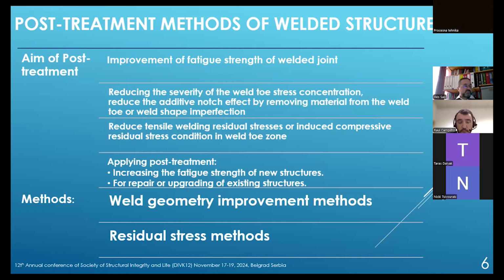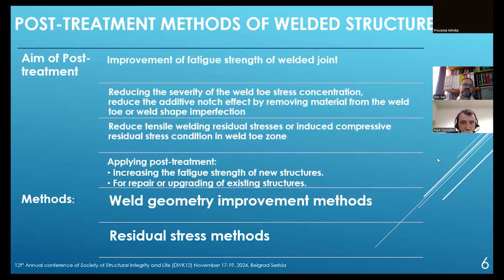What is important in the case of post-treatment is that some of the post-treatments can be applied not only after the manufacturing step, but also later when we detect imperfections during operation. If we make an analysis, and the analysis shows some criticality of these imperfections, post-treatment can also be applied during operation to increase the fatigue life of the product. Based on this, we can call them weld geometry improvement methods and residual stress methods, which we are applying in high-strength steel material.